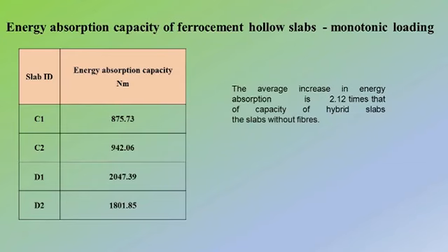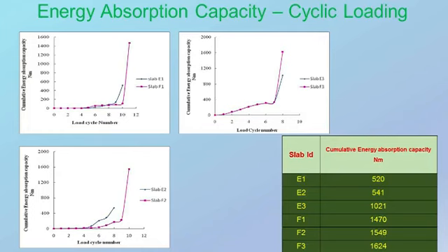Energy absorption capacity was also found, and the average increase in energy absorption capacity is 2.12 times that of hybrid slabs without fiber. So here we observe that the cumulative energy absorption capacity was more for slabs with fiber when compared to the slabs without fiber. So these are the cracks formed on the tension face of the slab.